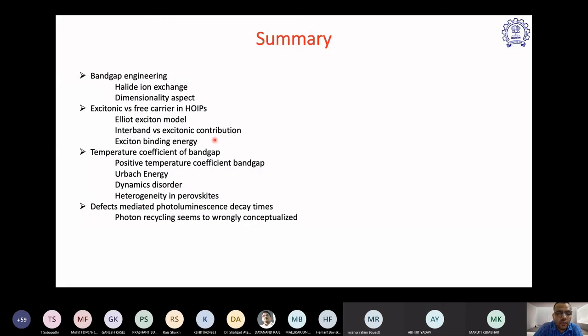Exciton binding energies are a function of n equal to 1, n equal to 2, n equal to 3, and of X equal to bromine, chlorine, iodine, and those can all be connected very well with the dielectric constants, which we can determine experimentally as well as theoretically. The temperature coefficient of the band gap, in huge contrast to what we have learned so far in textbook knowledge, is not negative but positive, because the lattice expansion coefficients are very high, and that does not allow electron-phonon interaction to dominate over the lattice dilation term. Urbach energy is very low. That suggests that these materials are really very ordered. Whatever disorder we have seen comes from dynamic disorder, because molecular vibrations are there in the voids of the octahedra.